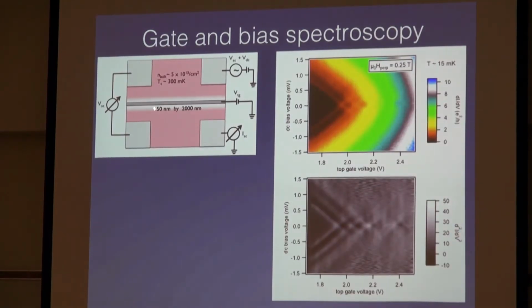So this pink region we've created with the ionic gating. This gives a little bit of stats about the material that we create with the ion gel. The bulk density is about 0.5 times 10 to the 14 per centimeter squared. If you dope strontium titanate that high, it becomes a superconductor. I think strontium titanate is the first semiconducting superconductor, which is an exciting knob to play with, and I'll talk a little bit about it towards the end of the talk.